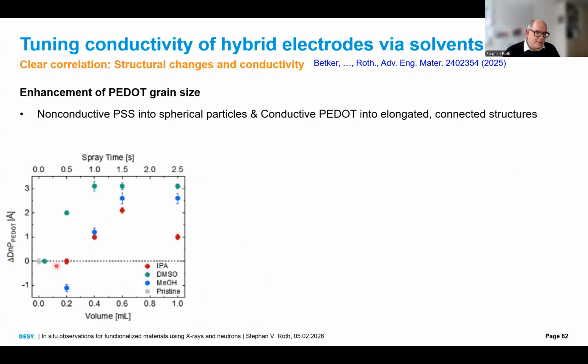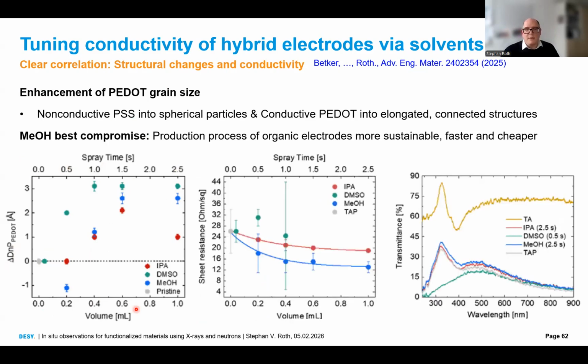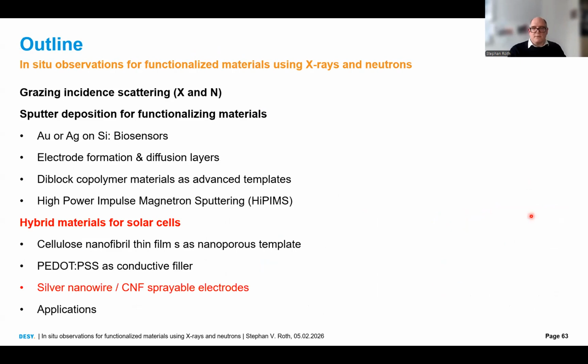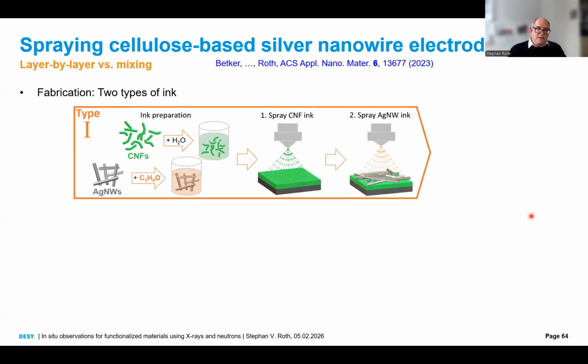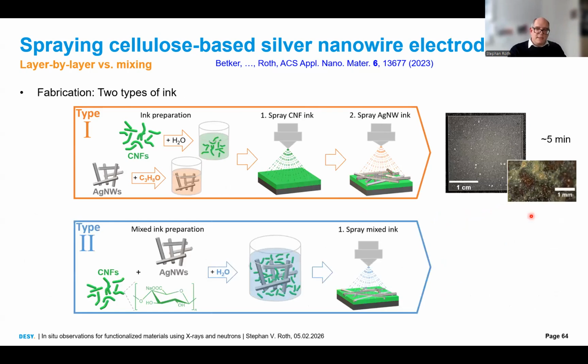This is the crystallite size change as a function of spray time and deposited volume. We can correlate this again with the sheet resistance and with the optical transparency. And with this, actually coming back to my first slide of sustainability, we can avoid nasty solvents but use methanol as the best compromise in terms of conductivity and transmission. Just to finish my talk, a very nice example here, how to spray an electrode layer.